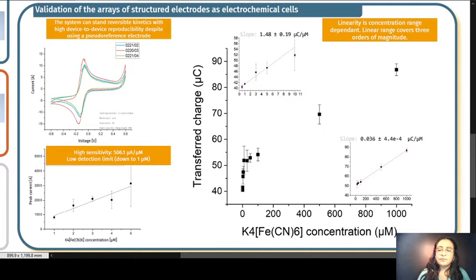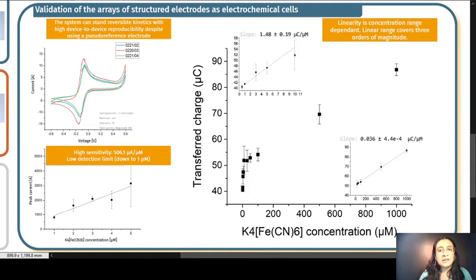Next, we made a calibration with ferricyanide in a wide range of concentrations, from 0.5 micromolar to 1 millimolar. We found good linearity, but concentration range dependent, and good limit of detection. Some devices have shown very high sensitivity towards the micromolar range. For example, 500 microamperes per micromolar in the 1 to 5 micromolar range. This is interesting because some biomarkers in physiological fluids are around this concentration.